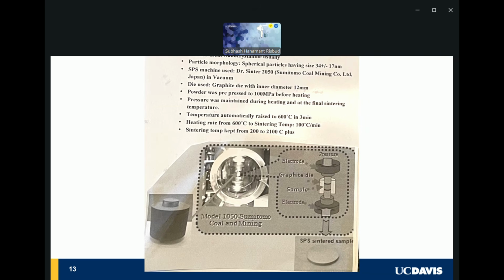The cooling rate is not very fast. I mean, you just shut the furnace off essentially, and so you're not in any sense of the word quenching anything. But it does raise the temperature up to as high as 2100 or even higher. And we've tried using carbides and borides in here to sinter as well as of course, the silicious materials.